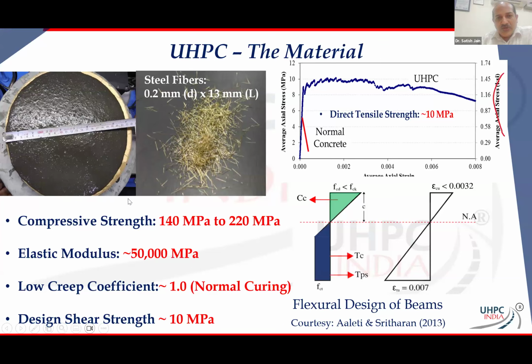Strength. Why do you get such a high strength? I've written somewhere in the range of 140 to 220 MPa. I mean, in the latest US code, they have even come down to 120 MPa for that matter. But the reason you get the high strength is a real tight particle packing of the UHPC. And when I mean particle packing, you're taking the fine aggregates, you're taking all the powdery material that is there in this mix. When I say powdery material, I mean cement, the pozzolans, like silica fume and maybe fly ash, maybe GGBS. And then, of course, any filler that you might have. And of course, the sand post that. When you have all these things together, all you do is a good particle packing so that the voids are lower. And when the voids are lower, you get a significant amount of compressive strength.